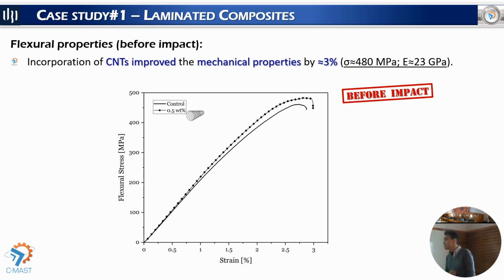Moving to the results, the first thing we did was to study the influence of the carbon nanotubes on the mechanical properties of our materials. As I said, we introduced 0.5% of carbon nanotubes in the laminate composites, so it was important to understand how their presence would affect the mechanical properties. We verified that, before the impact tests, samples with carbon nanotubes present higher mechanical strength and higher flexural modulus, so the addition of the carbon nanotubes improves the mechanical properties. So here we achieve a double positive effect.